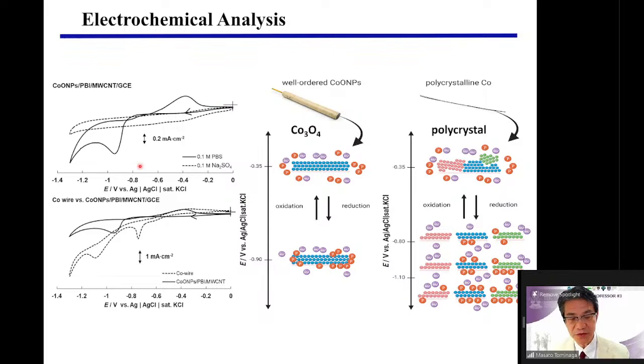And if we use the cobalt wire, what happens? When we use cobalt wire, the redox behavior is a little bit complex compared to the cobalt nanoparticles, because cobalt wire is a polycrystalline surface, right? So it means that there are many kinds of crystal surfaces. This phosphate detection depends on the surface reaction. So the surface is different, which means the reaction is a little bit different. The potential is a little different. So it makes it complex to detect the phosphate ion.